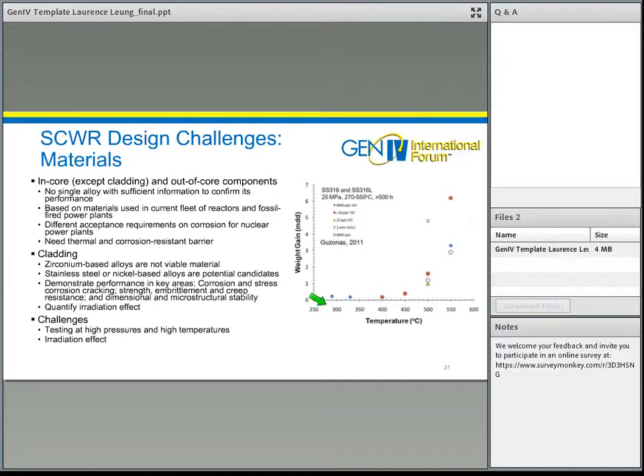This is the weight gain as a function of temperature in the autoclave. We vary from around 250 up to 550 degrees. You can see the weight gain, which simulates the corrosion characteristic, actually increases quite fast when you go to high temperature. We can test up to 550, but we still have a challenge testing at higher pressure and high temperature. For example, we don't have any autoclave beyond 700 degrees that can test corrosion. We started constructing a new loop that can withstand 850, so hopefully we can get some data at higher temperature.